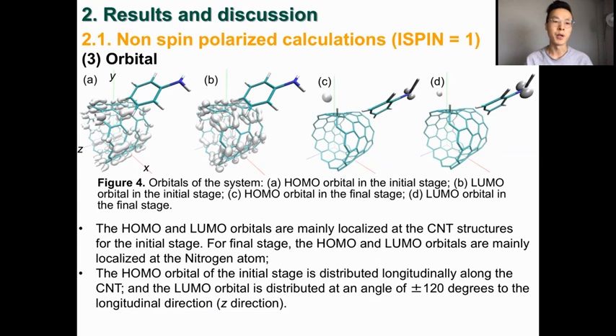Then I studied the orbitals of the system at these two different stages. As you can see from figures A and B, these are the orbitals of the system for the initial stage, and figures C and D are the orbitals of the final stage. We can find that the HOMO and the LUMO orbitals are mainly located at the CNT structures for the initial state. But for the final state, the HOMO and the LUMO orbitals are mainly localized at the nitrogen atom. The HOMO orbital for the initial state is distributed along the Z direction, as you can see from figure A, and the LUMO orbital is distributed at an angle of positive and negative 120 degrees to the Z direction, as you can see from figure A. This is the conclusion for the initial stage of the system.